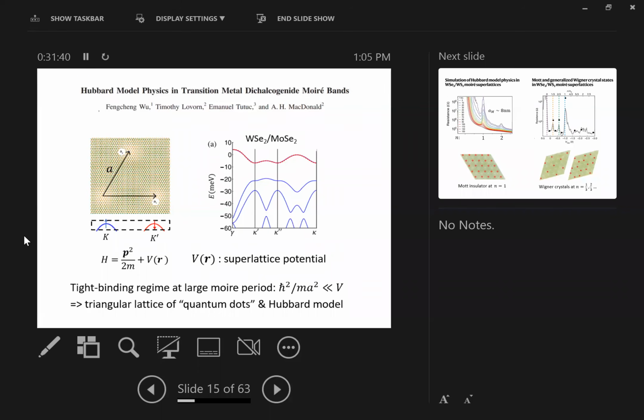If you look at a heterobilayer of TMDs, for example WSe2 and MoSe2, this is in a sense the simplest kind of Moiré band structure. Electrons in this particular system, the two layers have a band offset. The valence band top in one layer, WSe2, is higher than that of the MoSe2 layer. So if you dope holes into the system, the holes basically live in the WSe2 layer.